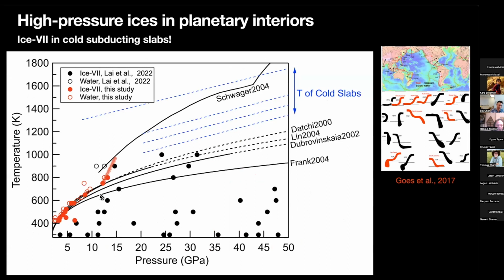So we have performed many experiments to determine the melting temperature by fine-tuning the pressure, and by melting and synthesizing single crystal. And then we can see that our lower temperature, lower pressure data agree well with previous work, but at pressures higher than 12 GPa, there appeared to be a kink, which is indicative that there may be a phase transition at a higher temperature for this pressure.